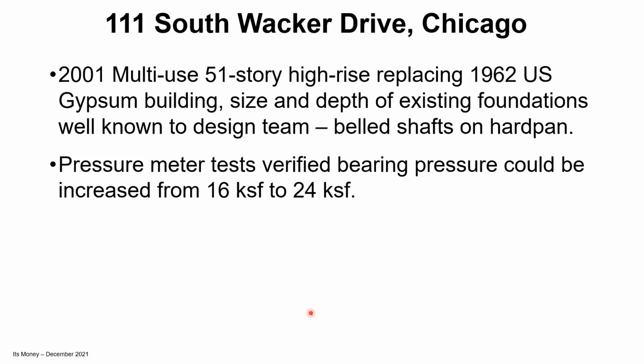One of the first things that were done was pressure meter tests to take a look at the capacity of the existing foundations. And Chicago codes have increased in allowable capacity over the years due to the amount of testing and construction verification that's been done over the last 40 to 50 years. So the pressure meter tests showed that we could increase the capacity of the existing foundation from 16 KSF to 24 KSF, which was quite significant.